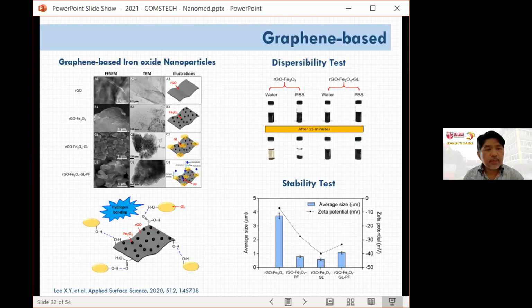With this finding, we also completed this study, and we can see that the complete system displayed high toxicity on A549 at an IC50 of 13.9, almost 10-fold lower compared to the MRC5. This finding can be explained by the fact that the polysaccharide also exhibits anti-cancer properties, which is capable of inhibiting the growth of cancer cells.